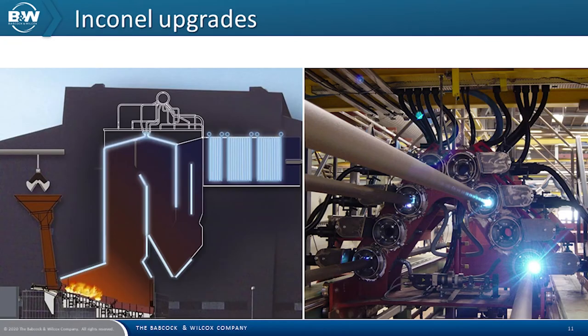Combustion of municipal waste results in an environment within the boiler that is extremely corrosive. Corrosion in waste-fired boilers is primarily caused by chloride compounds that deposit on the furnace and convection pass tubes in combination with high temperatures. Proper protection from corrosion in these areas is paramount to plant availability and the successful long-term operation of these key boiler components.